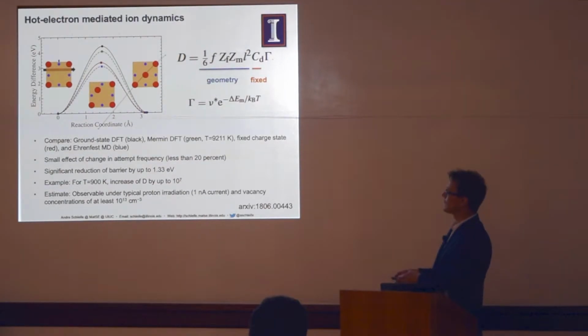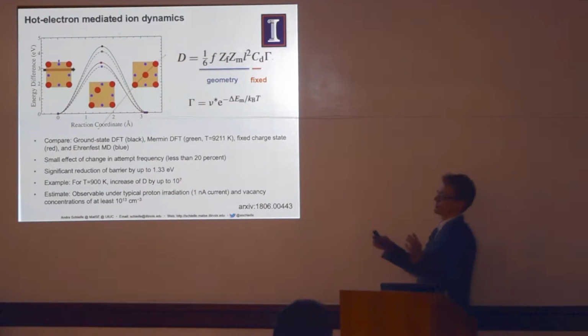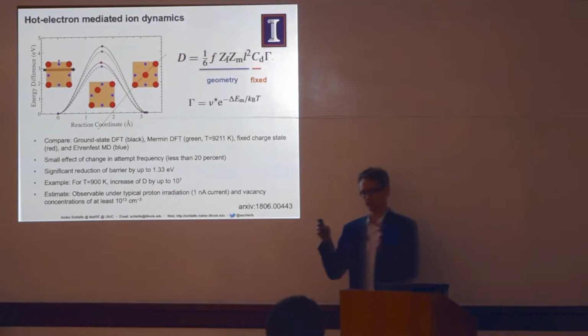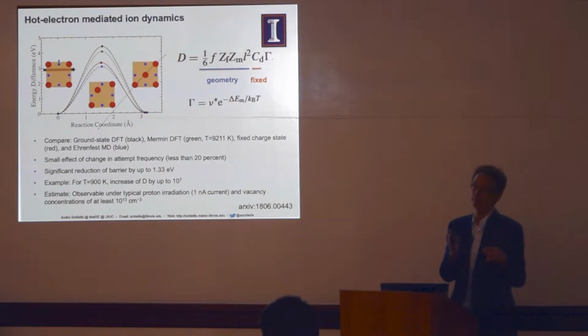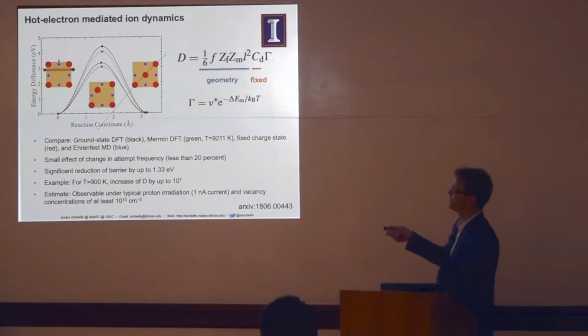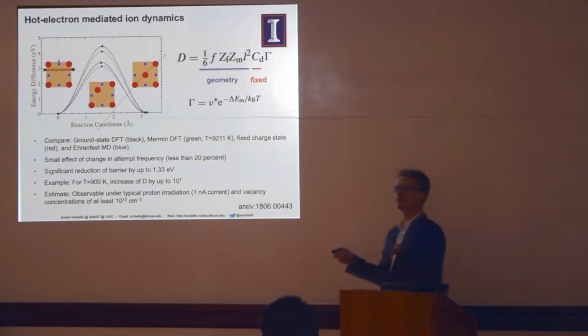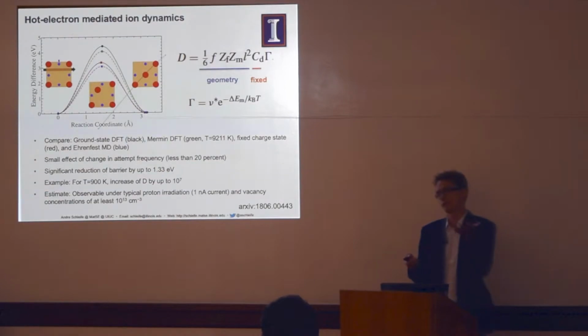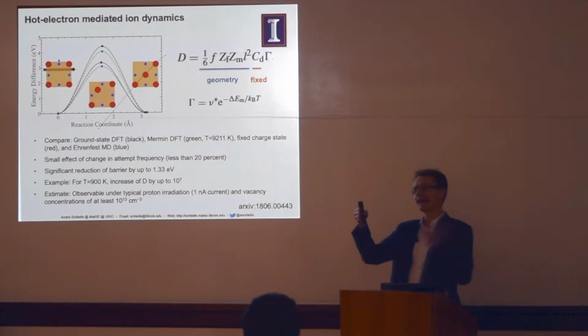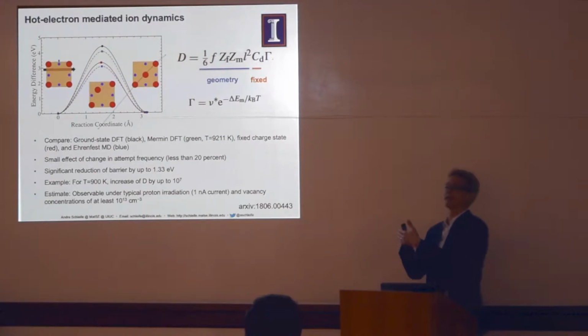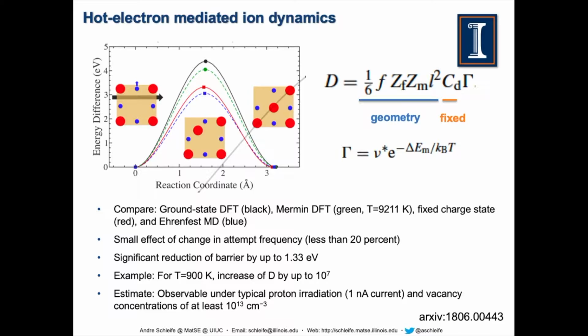And so now we're trying to find experimentalists that could verify that. That would be great. You can look at this 2 ways. You can either say we tune the beam energy and we look at a thin sample and see if we find an enhanced diffusion, right? Because it's very velocity dependent. Alternatively, you can say we come in with very high kinetic energy of the beam, and as the proton moves through the material, it slows down. And in other words, there is a certain part of the sample where it has the right energy to enhance diffusion. So in other words, you should observe position-dependent diffusivity.